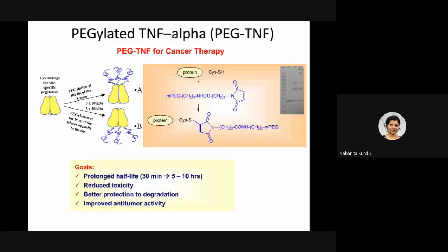And this is one way of making these nanoparticles targeting, what we call PEGylation, that is using polyethylene glycol. Polyethylene glycol is a very good molecule which is used over these nanoparticles for further attachment with the targeting molecules, right? And you see that the half-life of a drug, when you make it into polymeric nanospheres and nanocapsules, can be enhanced from 30 minutes to 5 to 10 hours. So the 50% concentration was reduced within 30 minutes when administered using, say, a gelatin capsule or something like that. But when it is put in a polymeric nanocapsule or nanosphere, the half-life is increased to some 10 hours, from 30 minutes to a minimum of 5 hours. So a 4.5 hour enhancement in half-life minimum we get, right? So these sorts of advantages.